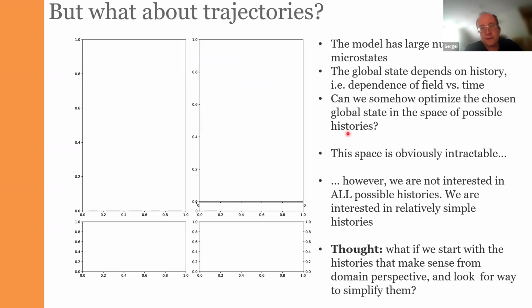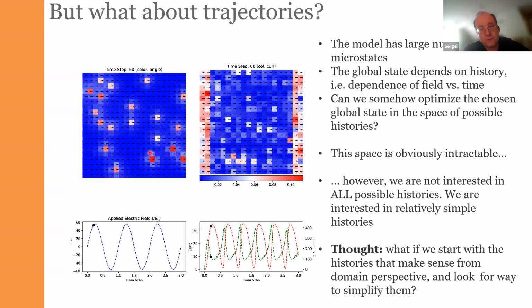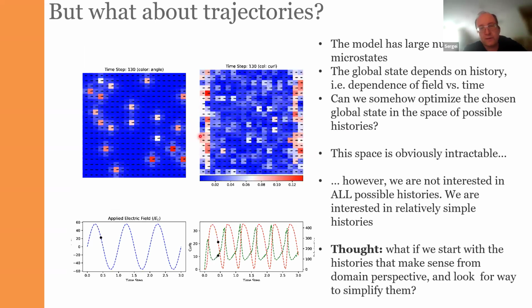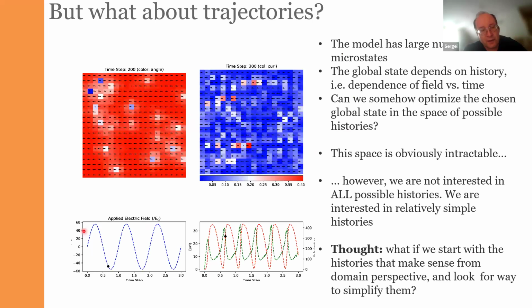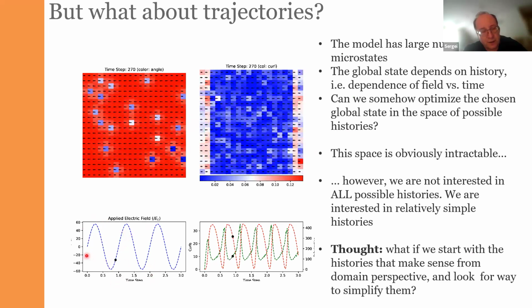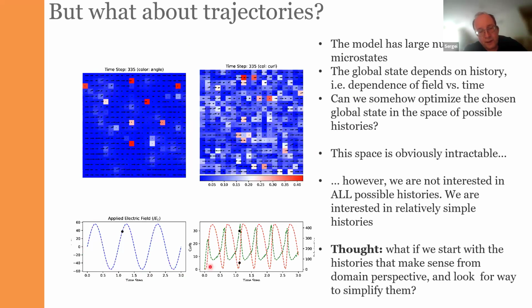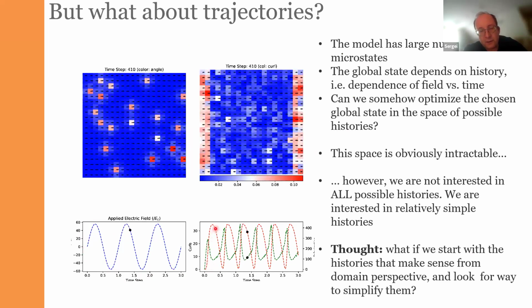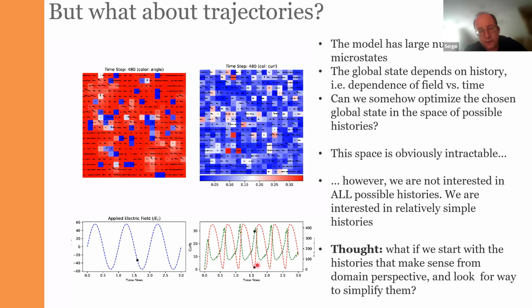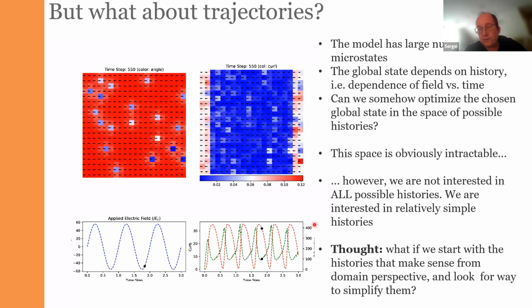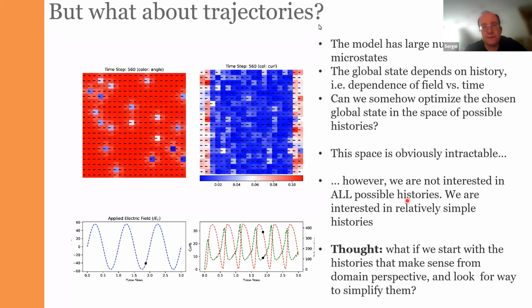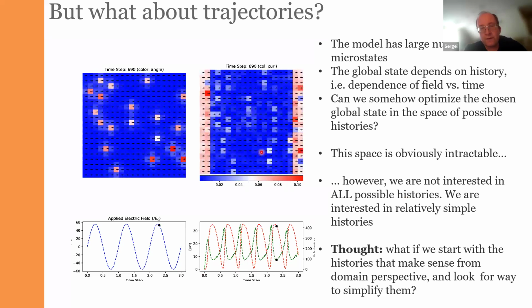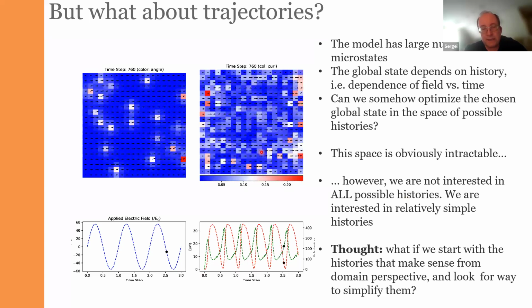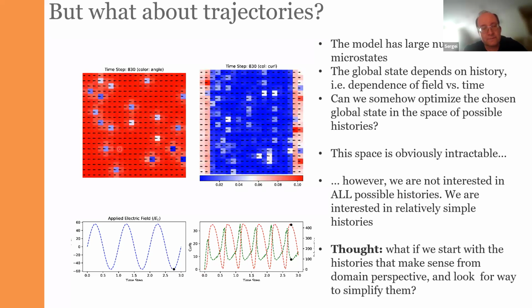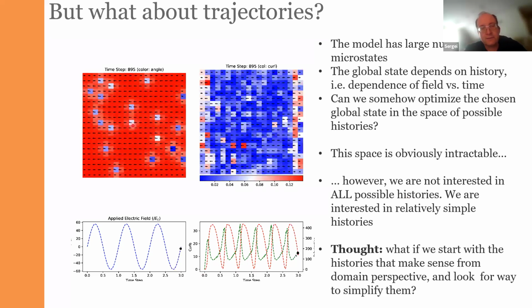The important thing is that this model allows us to model things like hysteresis. So we can introduce noise in the system. We can apply the external electric field. This is how the electric field is changed, and this is how the total polarization changes, the red curve. And the green curve here is the curl of polarization. Curl is interesting because according to symmetry, curl in this system should be 0. But practically, because there are defects, they result in symmetry breaking, and the curl can become not 0.